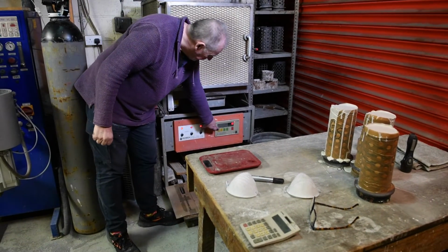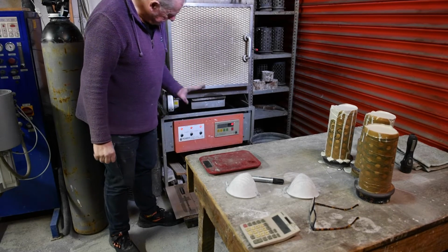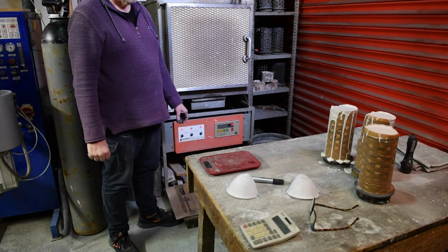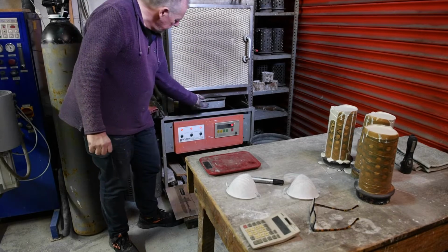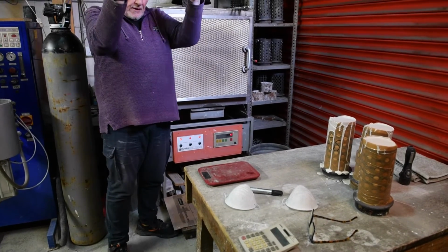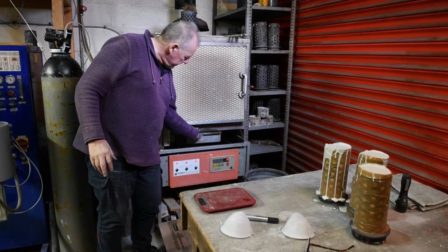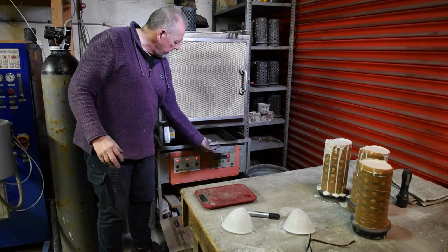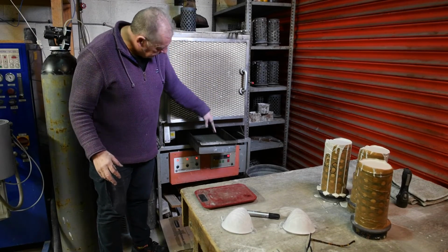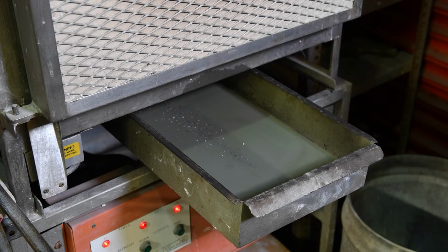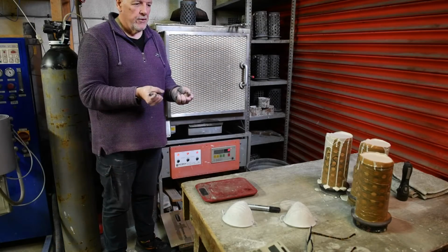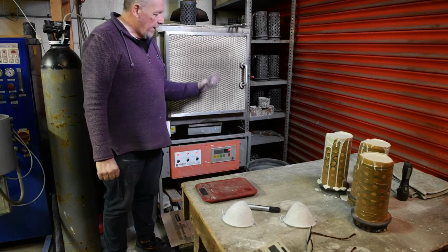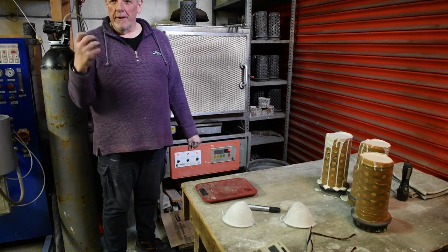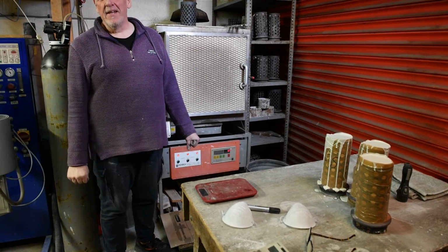So we can then start the kiln, and it will do all of its process overnight. In the bottom of the kiln, it's slanted, and the main amounts of wax actually melt out and flow into this collecting tray underneath. So it's only the remaindered wax inside that actually burns away to carbon monoxide and carbon dioxide. And that will be 12 hours later, we will be casting, which will be the next morning.